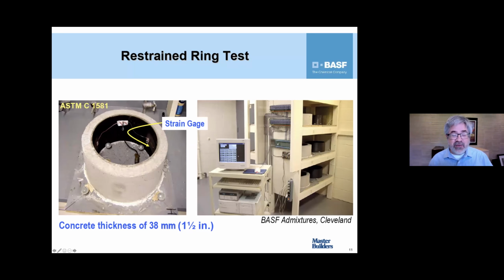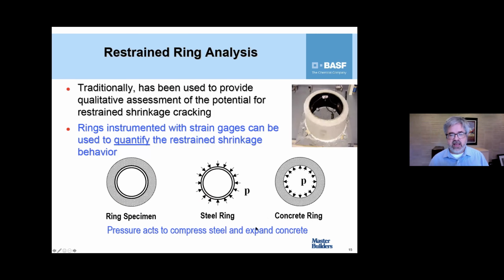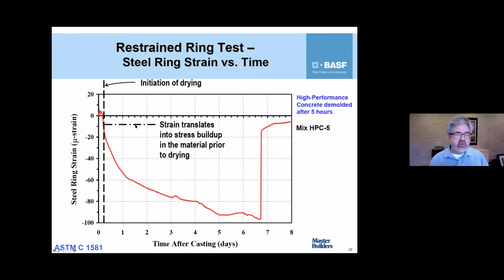These strain gauges are really sensitive and they can pick up that squeezing action that the drying concrete places on the steel. It's amazing. And that gives us a chance to measure that stress, and we can track that stress with time. In this case, we get to about 6 days, and we keep building stress more and more, and then boom, something happens. What happens is called a crack. The ring of concrete breaks, all that stress is relieved, and we see it in the data.